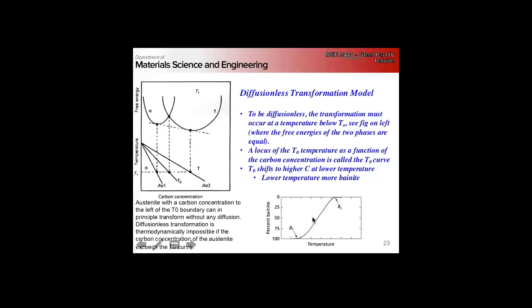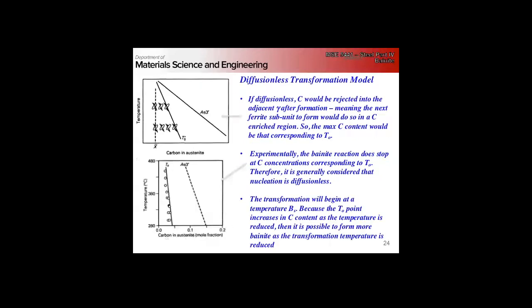as if at some intermediate temperature, we hit the T naught carbon concentration in our austenite before we can continue. And if that's actually true, we should see that our concentration in the austenite should stay basically at that T naught line, and we do see that.